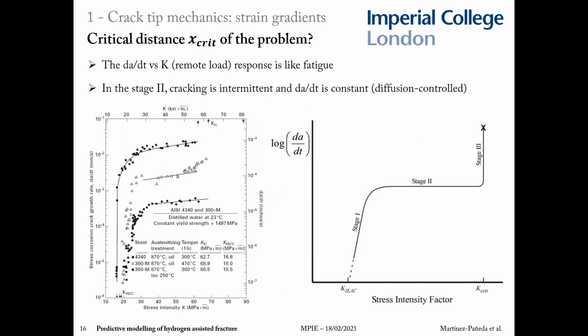And we can determine the critical distance at which cracking occurs by interpreting experiments. So hydrogen-assisted fracture is a little bit like fatigue, in that if you plot the crack velocity versus the applied stress intensity factor, you get this 3-stage region. A first stage immediately after cracking, where the crack speed grows fast with applied load. A stage 2, where the crack speed is insensitive to the remote load.